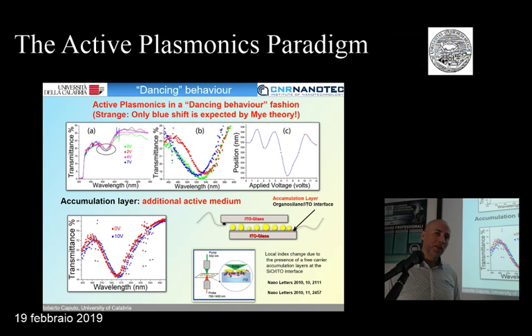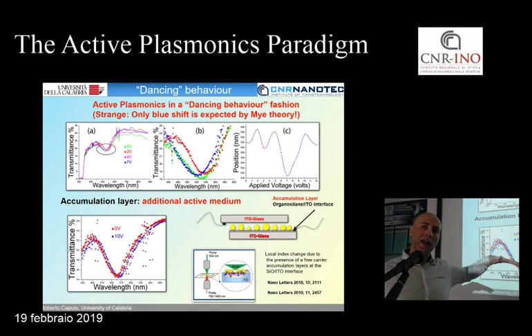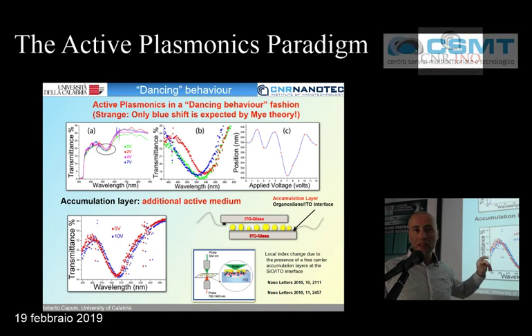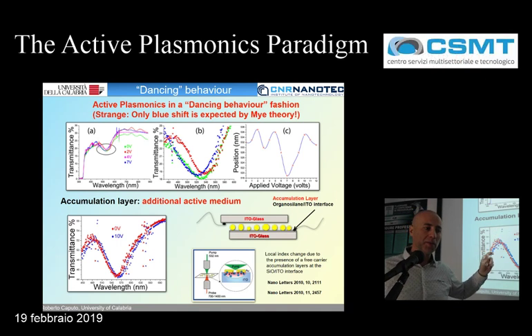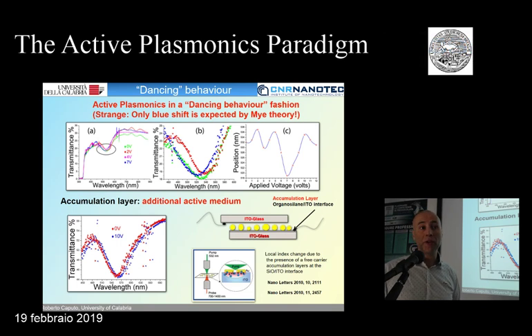The point is that in this case, there is the creation of an accumulation layer at the interface between the glass and the ITO layer which is on top of the glass for applying the field. This is a competing mechanism of tuning, because this accumulation layer creates a local change of the refractive index, which is competing with the change of refractive index of the liquid crystals.